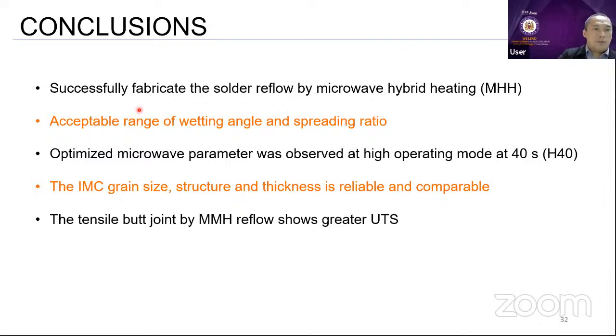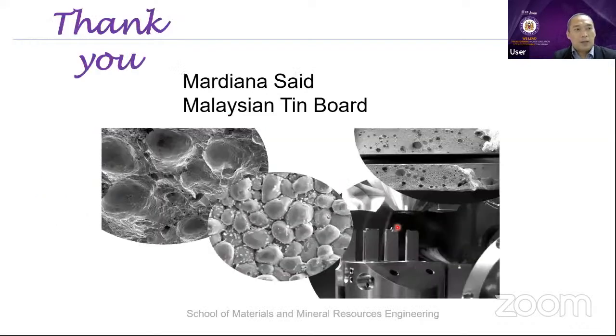Okay, we were able to successfully fabricate the solder reflow by microwave hybrid heating, with acceptable range on the wetting angle and spreading area. The optimized microwave parameter was observed, and the best is H40. The IMC grain structure and thickness are reliable and comparable to the conventional one, even better. The tensile of the butt joint by MHH reflow shows a great improvement over the conventional. At the end, I would like to thank my student for his excellent work, and I also thank my sponsor, the Malaysian government.